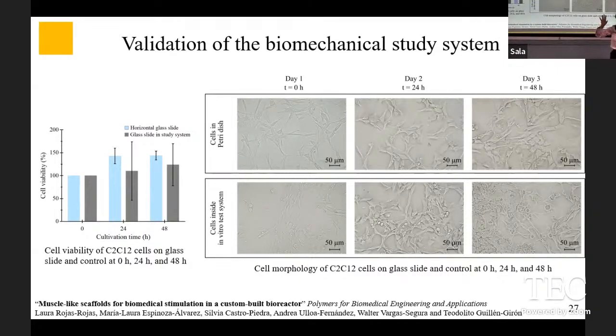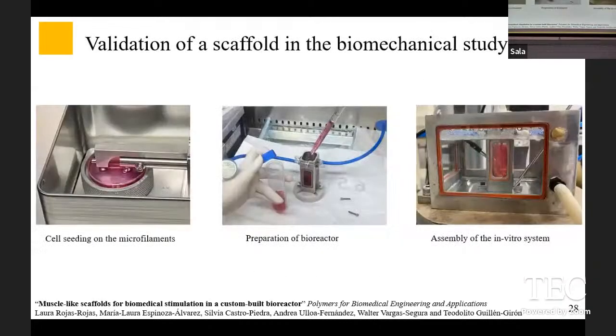So at least up to here, the bioreactor was not toxic, was properly sterilized, and also had proper temperature and proper carbon dioxide circulation. Once we had done that, we went to test the scaffold. So now we were sure that the bioreactor was working, so now we went into testing the scaffold. So we did a cell seeding procedure on the scaffold. Then we did the preparation of the bioreactor and did the whole assembly together.